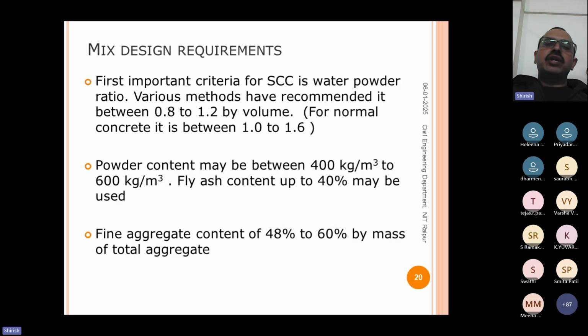Powder content may be between 400 to 600 kg. Now, if viscosity modifying admixture is used, we may not require such a high quantity of powder content. Yes, fly ash is a very, very good material for self-compacting concrete. What is the benefit of fly ash? It is a spherical and glassy material. Glass means very smooth, and spherical means it acts like a ball bearing. So that helps in increasing the workability, increasing the viscosity, and also keeping the flow high. That is the benefit of fly ash.